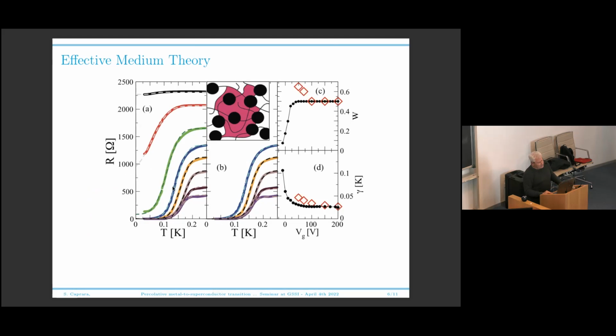So as you see, the effective medium theory is quite satisfactory. It gives a reasonable description of the data. What is not really satisfactory with this solution is this fact. As you see, the transition is always very tailish. Even when the transition finally occurs, you see that the resistance goes to zero with a very long tail. Now, with a Gaussian, but even with other distributions for your critical temperature, to obtain this tail you must exhaust all your distribution, which means that the weight of the superconducting cluster is close to the percolation threshold.